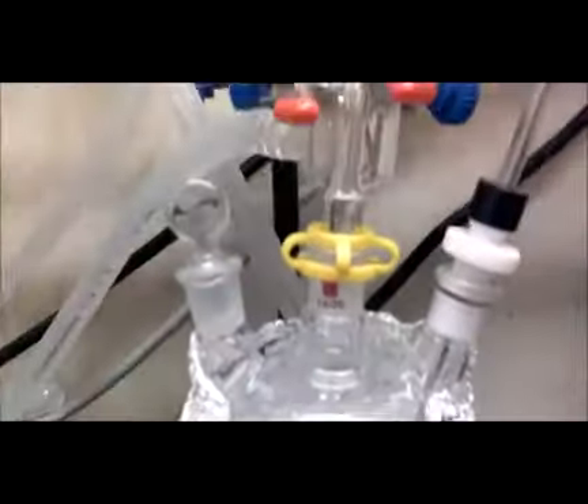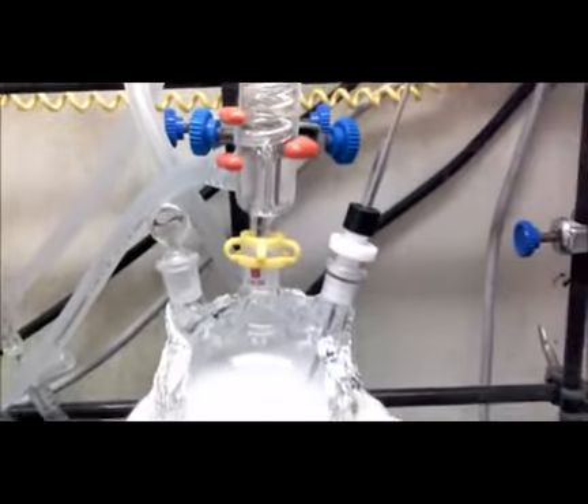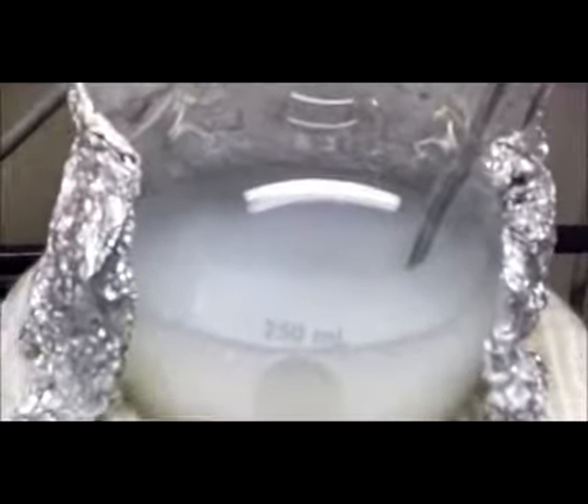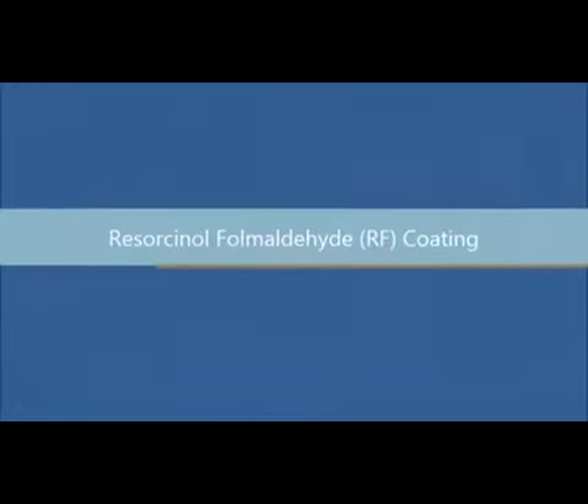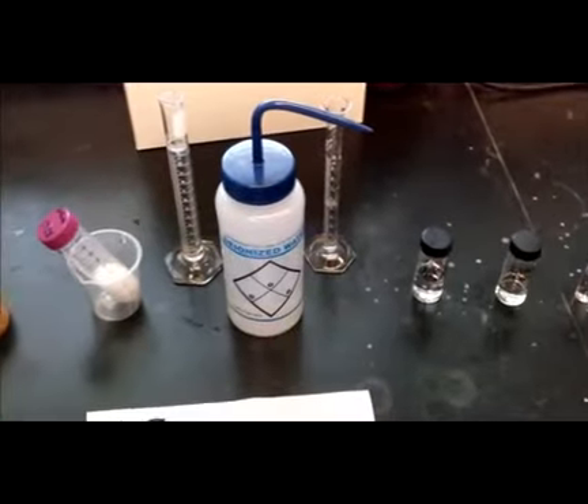After it has refluxed for an hour and 15 minutes, we let it cool and do 1 wash with water and 2 with ethanol, and then disperse it in 50 milliliters of ethanol. We then prepare to do the RF coating.